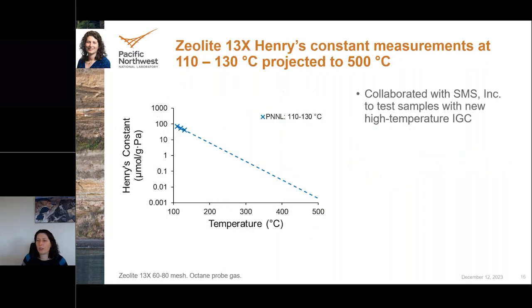So up to this point, the measurements I've been showing have been of materials at temperatures less than 150 degrees, and that's because of the upper limits of our instrument. Based on these results at the lower temperatures, we have extrapolated what the values would be at higher temperatures. And so what I have shown here is zeolite 13X, the synthetic zeolite, and we have our measurements marked with the blue X's from 110 to 130 degrees Celsius. And then I just did a linear extrapolation out to 500 degrees Celsius.